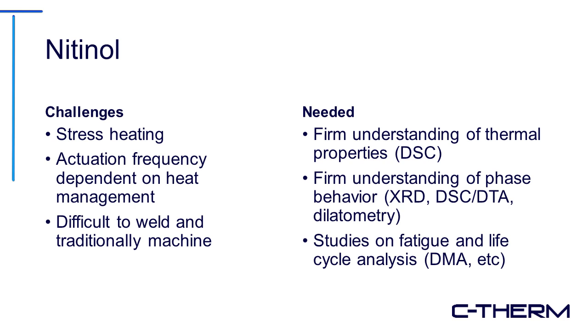So there's a few challenges when you're working with nitinol. One of the first ones is that it tends to stress heat, and the actuation frequency, because it stress heats, is dependent on thermal management. If you don't pull that stress heat away efficiently enough, it's not going to be able to actuate as often. It's also traditionally been considered pretty difficult to weld and also machine. So you need to understand the thermal properties very well, which you can do by DSC. And you also need a firm understanding of the phase change behavior, which can be done by a combination of techniques, such as XRD, DSC or DTA, and dilatometry.